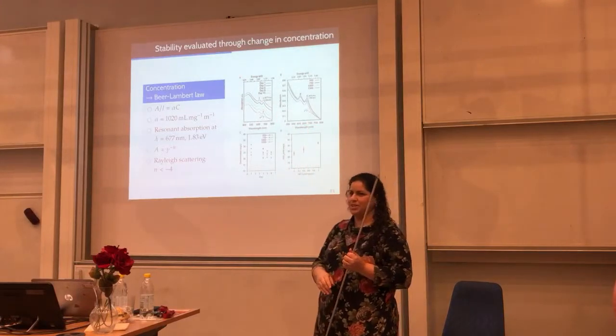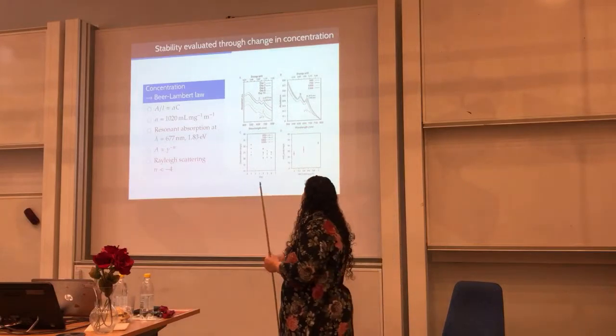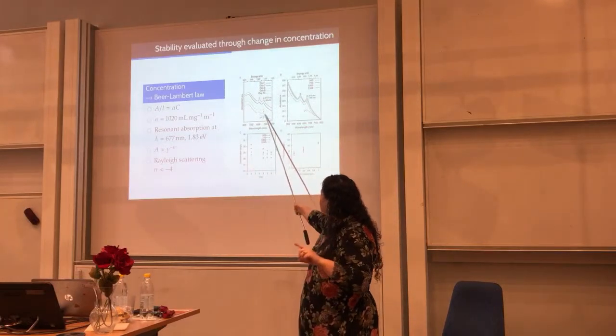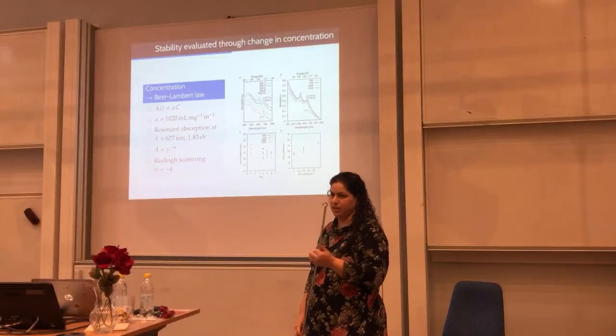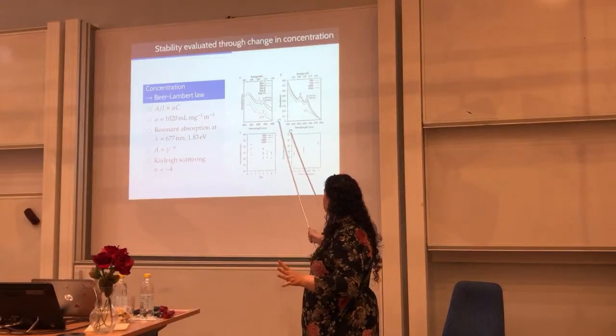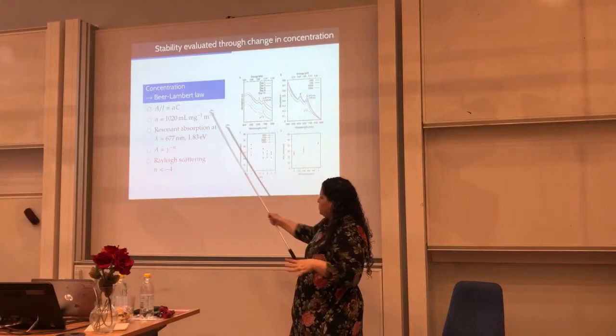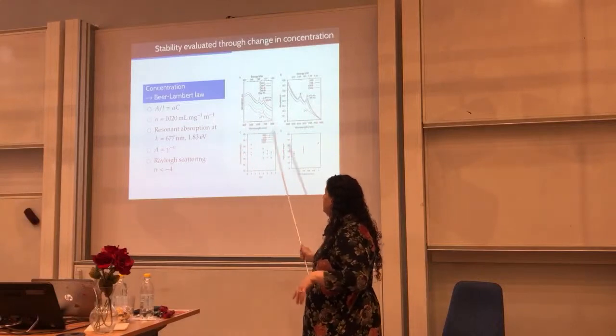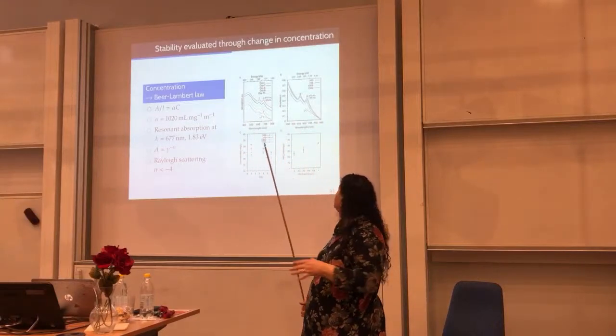And why do we measure the absorption at this particular position? Because that's the position of the band gap for molybdenum sulfide. So this measurement doesn't only help us to estimate the concentration, but it also tells that this is molybdenum sulfide in this portion.